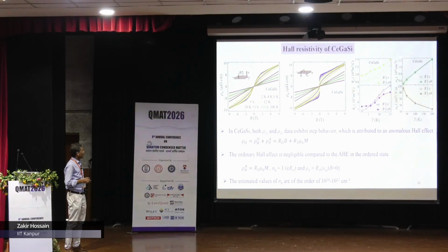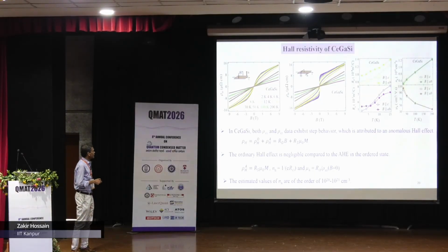This is Hall effect. And in the Hall effect also, we find that the Hall signal is not linear in field. If it is only normal Hall effect, the Hall voltage, rho H, will be linear in magnetic field. So here we could analyze in terms of one linear component, but there is something proportional to magnetization. One requires these terms proportional to magnetization, and that's why we say that there is anomalous Hall effect present in this compound.